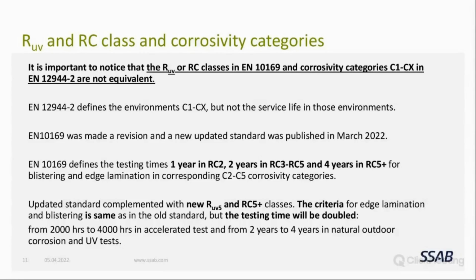The updated standard is complemented with the new RUV5 and RC5 plus classes. The criteria for edge delamination and blistering are the same as in the old standard, but now the testing time is doubled from 2,000 hours to 4,000 hours in artificial tests, and from 2 years to 4 years in natural outdoor corrosion and UV tests.